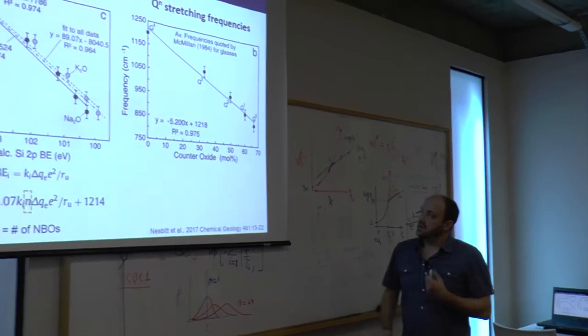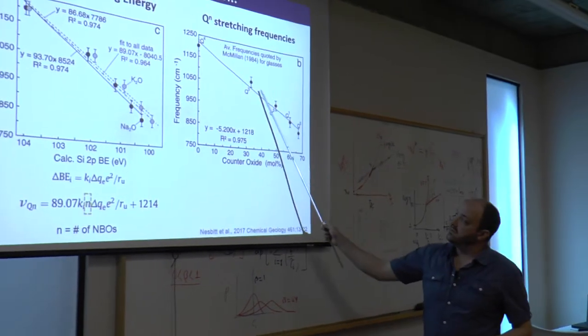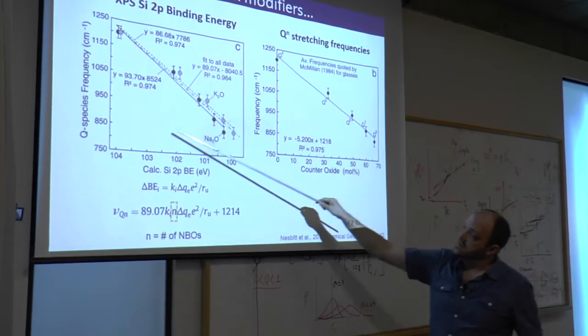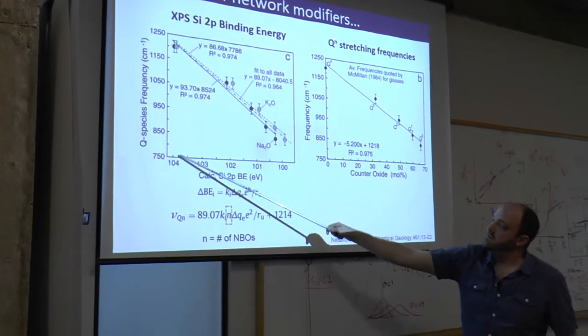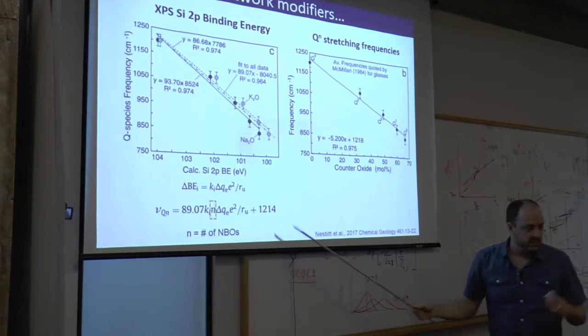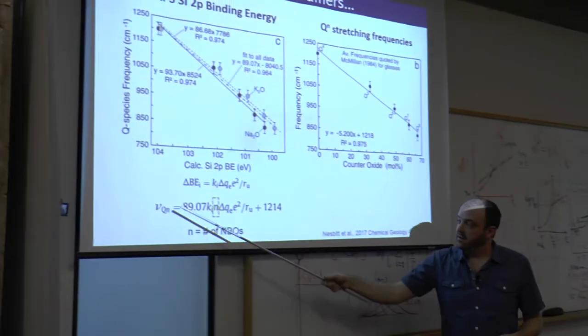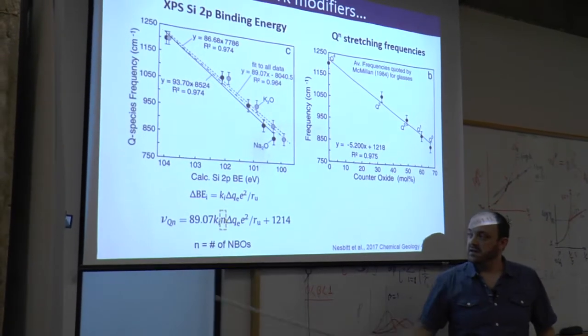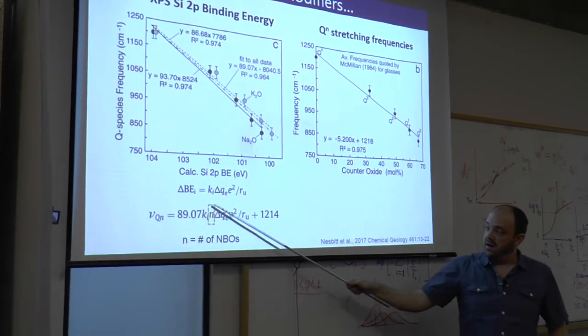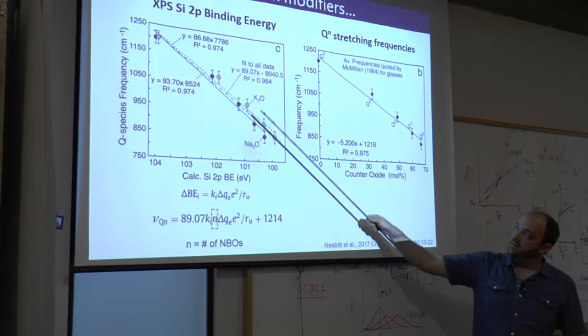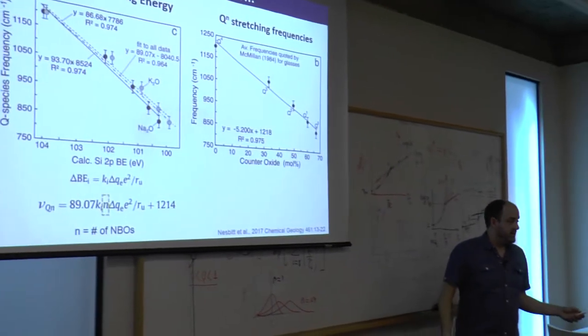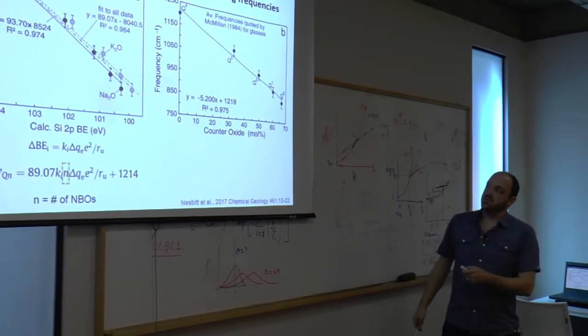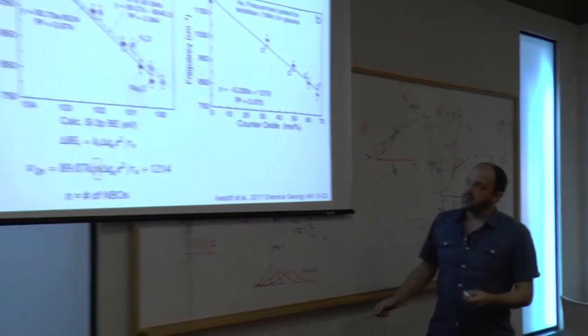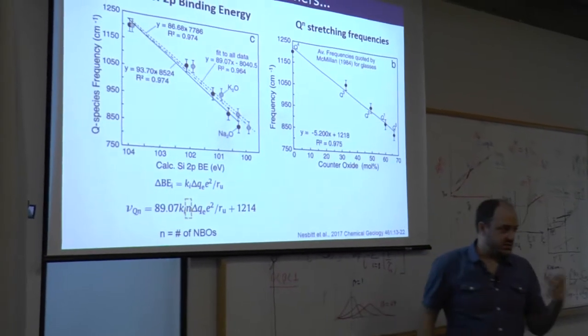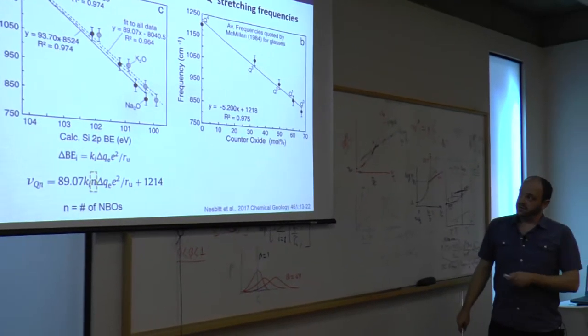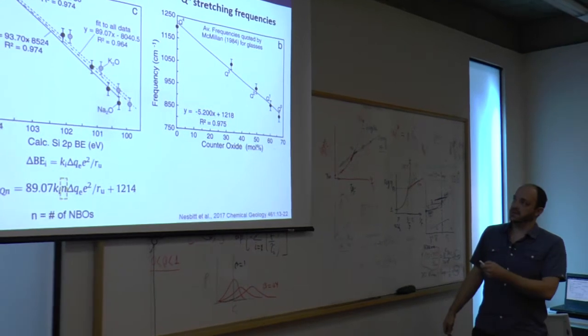And the other thing that these guys added is they actually compared the stretching frequency for these Q species to, this is the same Y scale, but this is the binding energy of the 2p electrons. And I'm not an expert in XPS, so I'm not going to go through what this means, but they created this relationship to actually determine the strength of the vibrational frequency of the QN species as a function of the number of bridging oxygens. And this has been done for potassium and sodium, but it's still an open area of research that's going on. But this is to point out that there is a direct relationship between the frequency in the Raman and the actual strength of the bond between the different QN species. There's a little bit of shift, but not that much.